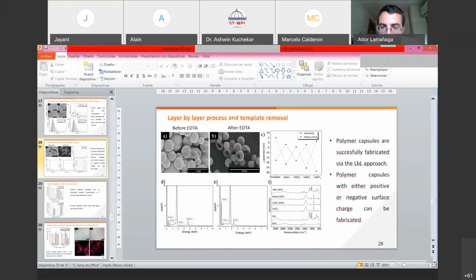This one, yeah. So here, what we found is that if you see the template, initially it had a negative surface charge because we use polystyrene sulfonate for the fabrication, and as we incubated with the manganese dioxide nanoparticles, it changed to +5 because of the positively charged nanoparticles within our template, right? But then if you look layer after layer, I wouldn't say there is a huge difference between the zeta potential, right?